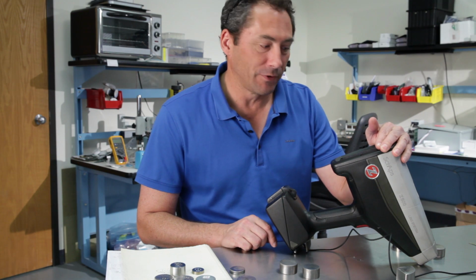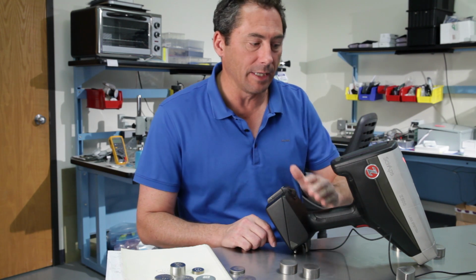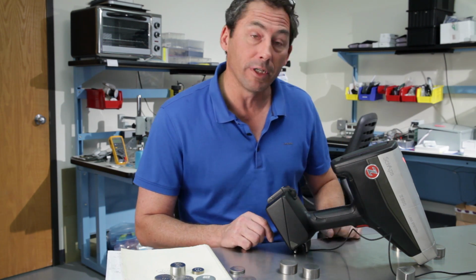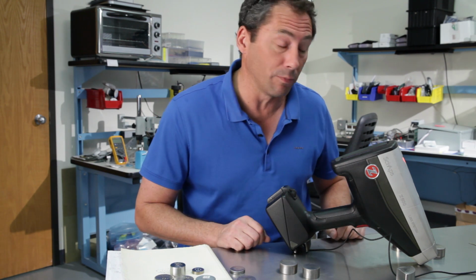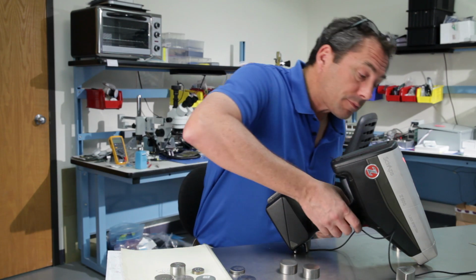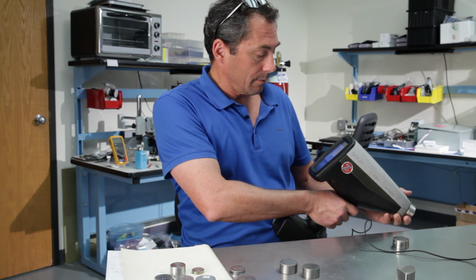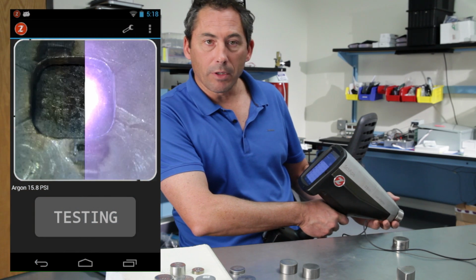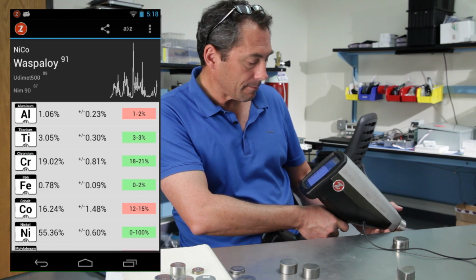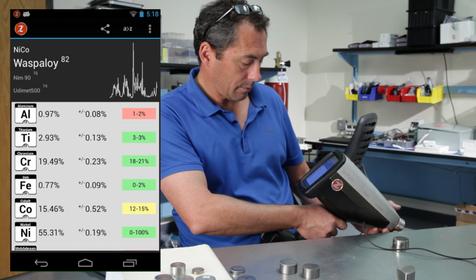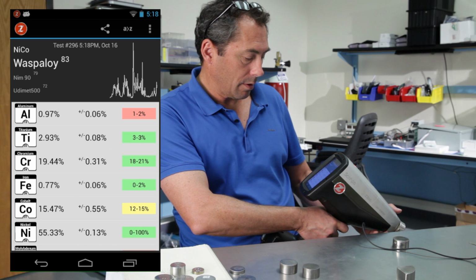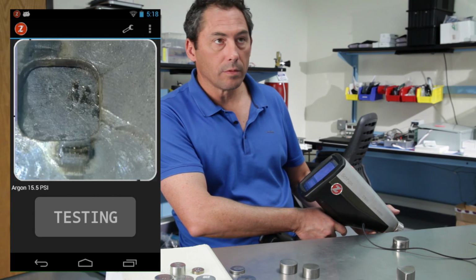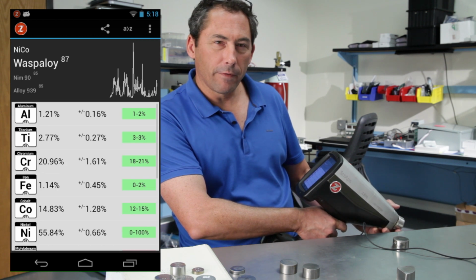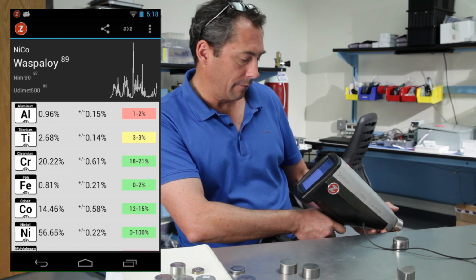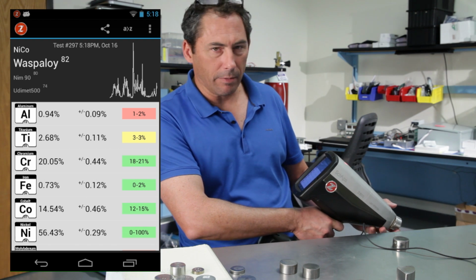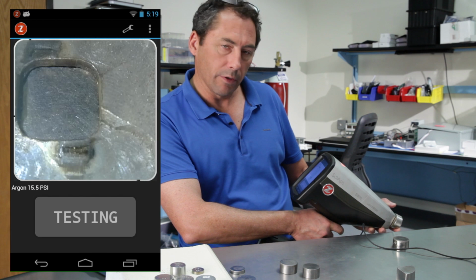The last thing I want to show for some nickel alloys is, again, with the argon, the repeatability you can get even on nickel and some of these nickel cobalt and super alloys. So I'm going to shoot this Waspaloy 3 times. Do three quick shots. Another one. These are running about 4 to 5 second tests, which is about the longest test time you'd ever need for the laser. I think these are probably some of the most complicated alloys that you're going to run into, especially for LIBS.